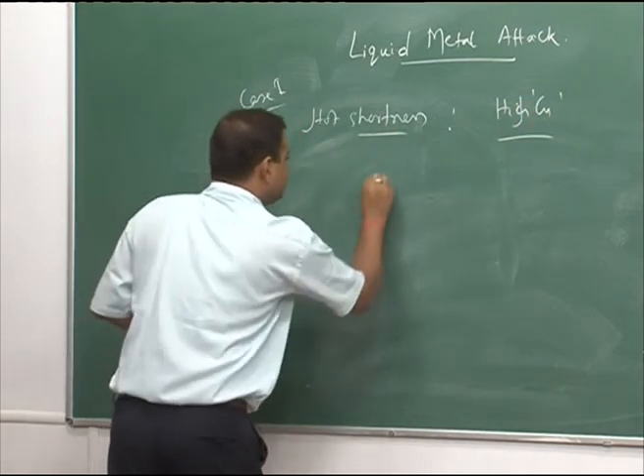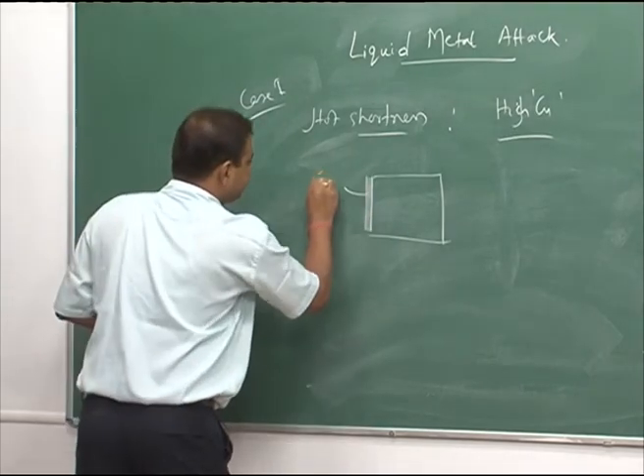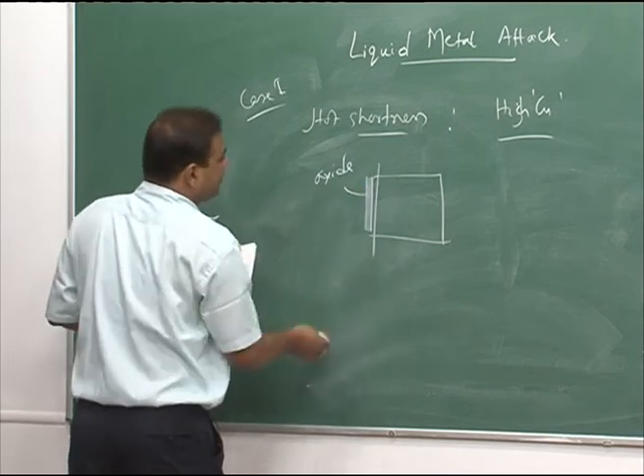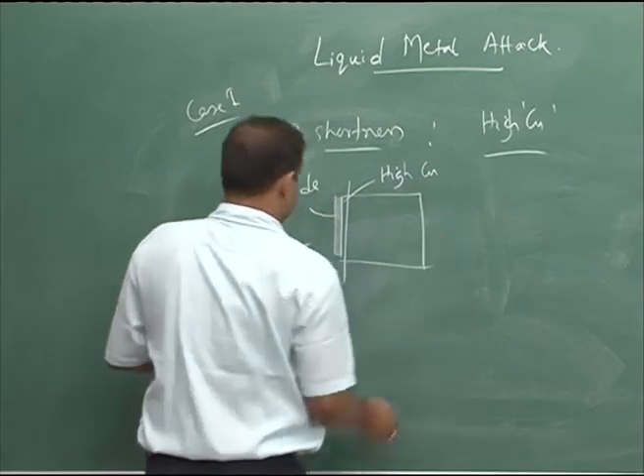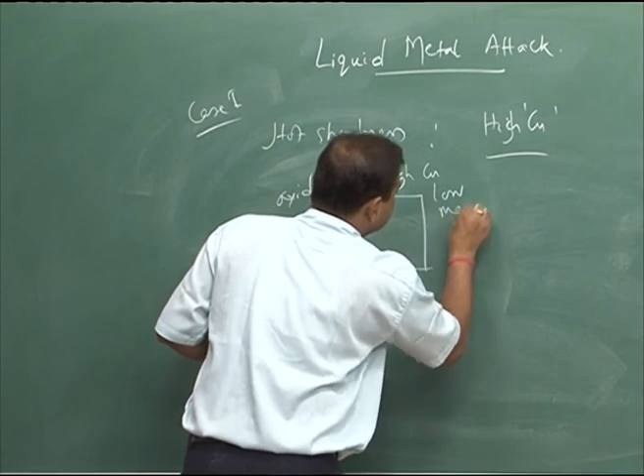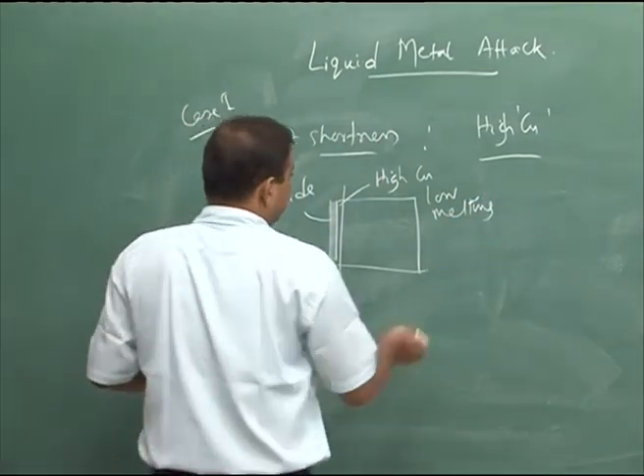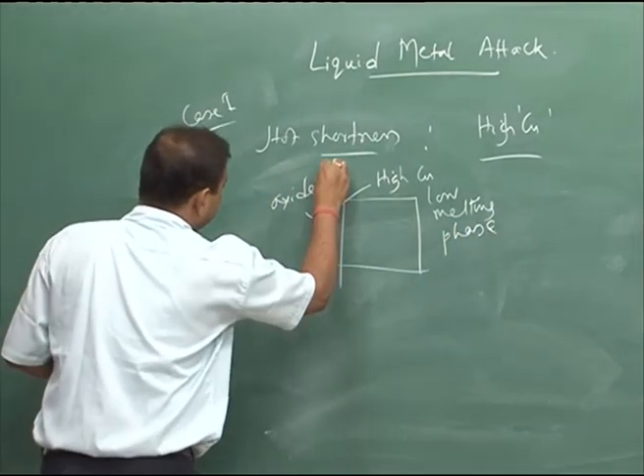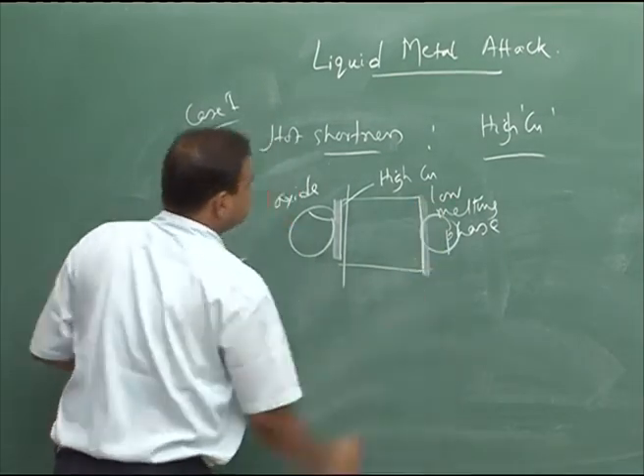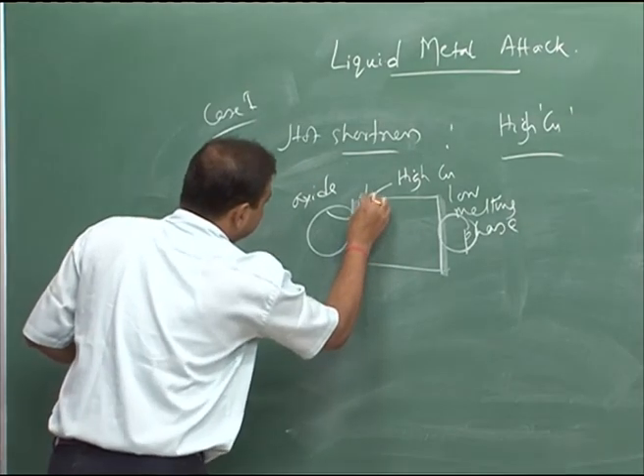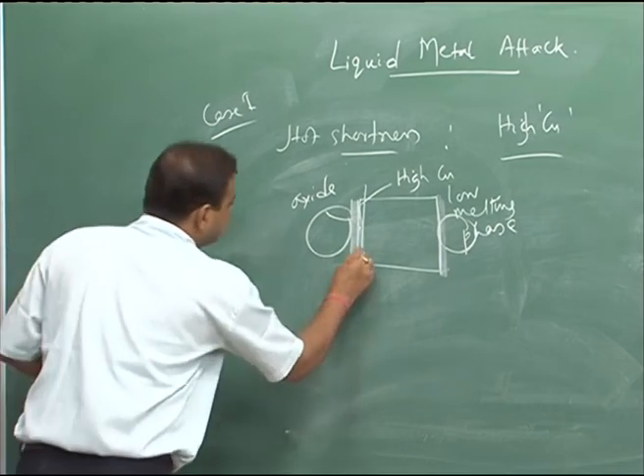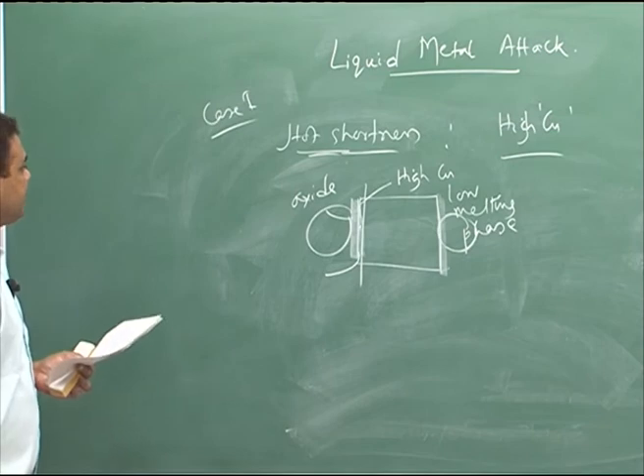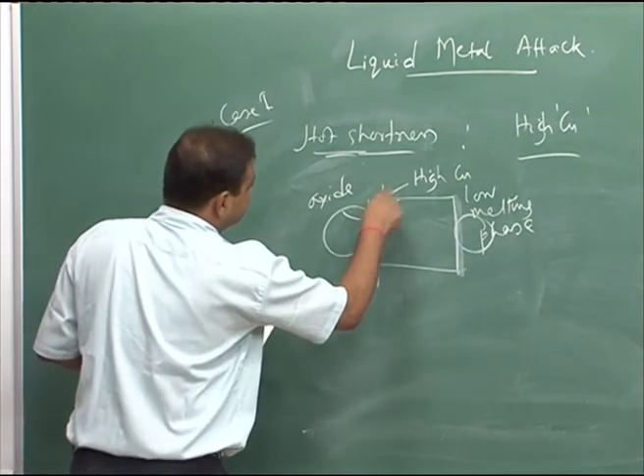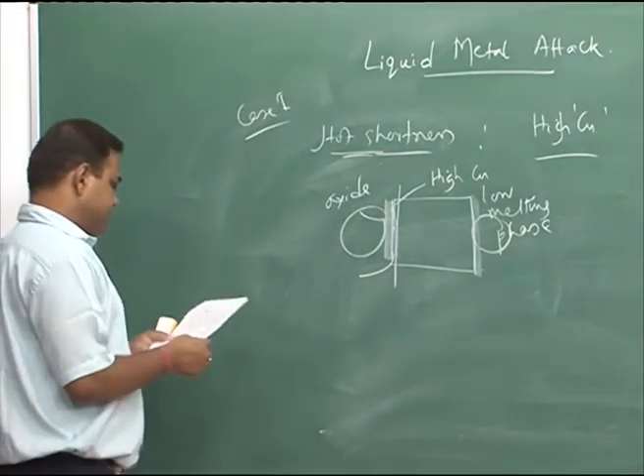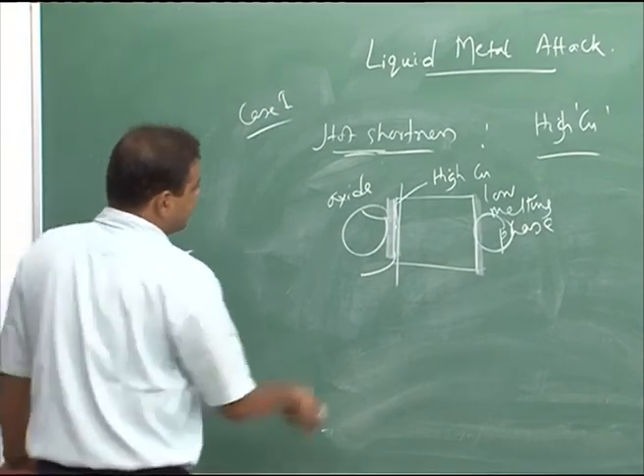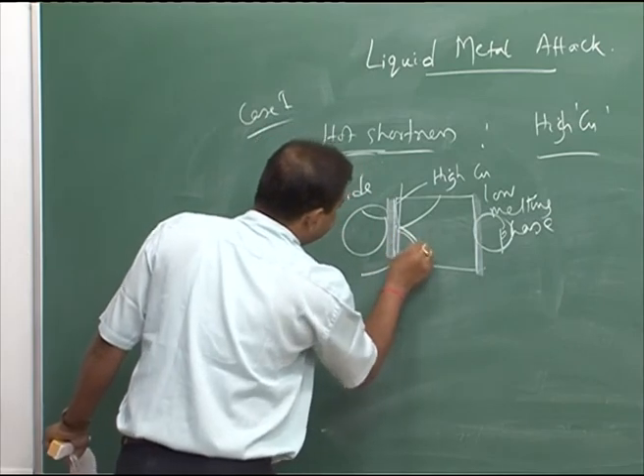in the steel, so you have this steel and on the surface you can have oxide, and just below the surface in this part you can have high copper compound formation, low melting phase. So, now if we roll it like this, this thing also can happen this side also. During rolling, this one would form a liquid because that is a low melting phase, and that can lead to hot shortness. This is one example of liquid metal attack, and that liquid metal is nothing but this high copper low melting phase which is getting melted, and that phase can penetrate along the grain boundaries.